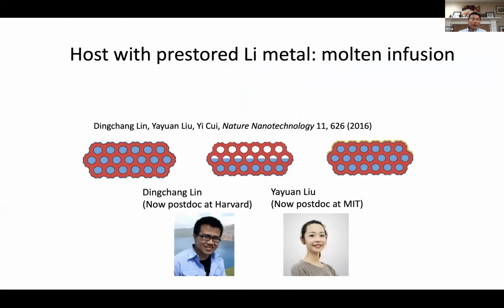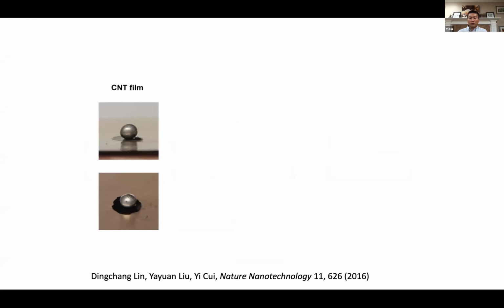With this type of host concept, we extended it to ask: can we generate lithium metal inside a host without using electrochemical deposition, but during chemical synthesis? This motivated us back in 2016 to develop molten lithium infusion into host materials. But what host materials to use? We used carbon nanotube film, carbon fiber, mesoporous carbon, and carbon nanofiber right here.